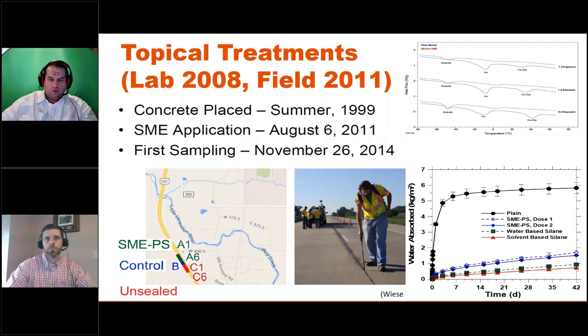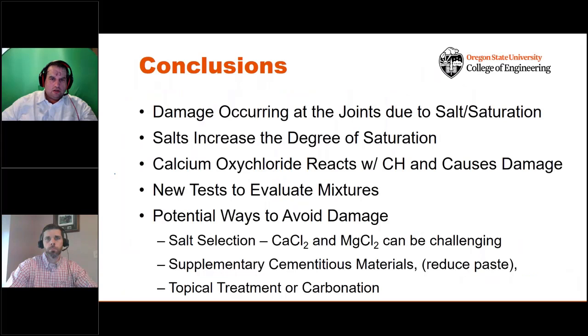All right. In addition, what we can do is we can actually use a topical treatment, and here's a soy methyl ester polystyrene that's working very, very well to prevent moisture from getting into the concrete itself and causing this damage. So in conclusion, a lot of the damage that's happening at the joints is due to